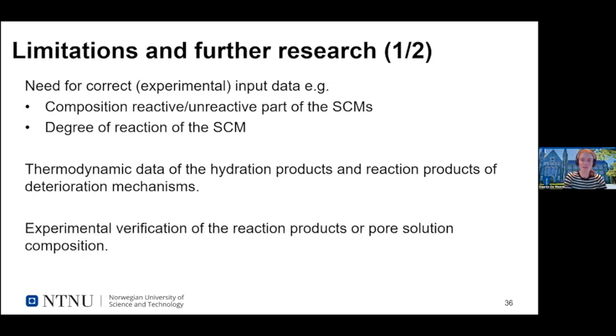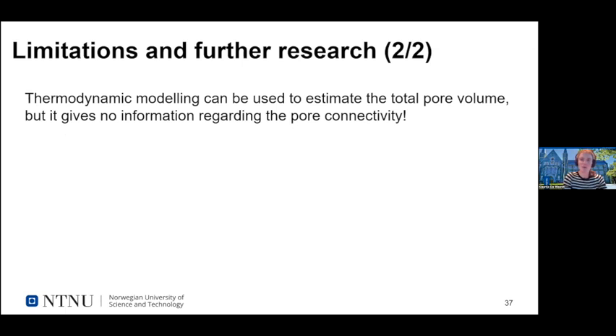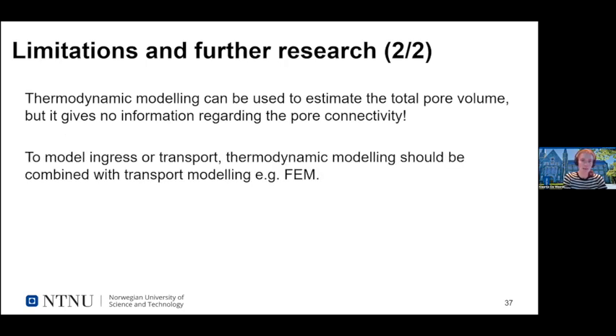So that's why I really want to stress that you should always try to combine GEMS with experimental verification, so that you can identify the reaction products you predict. And similarly, the pore solution composition is a very nice verification of your model. I mentioned when talking about carbonation that thermodynamic modeling can indicate a pore tightening effect. But there it's important to be aware that thermodynamic modeling only predicts the total pore volume. It doesn't give you any information on pore connectivity. So if you want to do transport modeling, you should combine your thermodynamic modeling with a transport model and with a characterization of your pore connectivity, because GEMS can't do that.